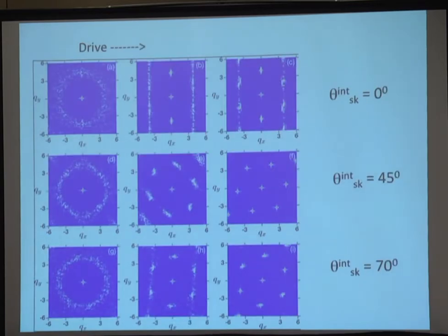So if we're using neutron scattering on this, what would you see? This has essentially already been seen for vortex systems, different vortices in superconductors. At low drive, when the skyrmion lattice, or the vortex lattice, is disordered, you get a ring shape. You drive it faster, you get into a moving smectic phase, and then at even stronger drive, you get to a moving crystal. In the skyrmion case, you see something similar, you see a rotation in the lattice, and you also see the system reorder to a better, more ordered triangular lattice than you see in the vortex case.